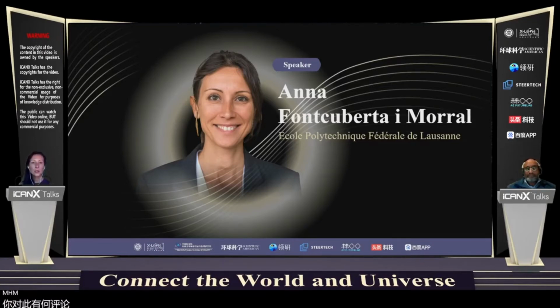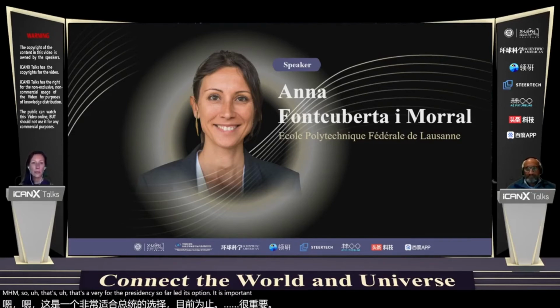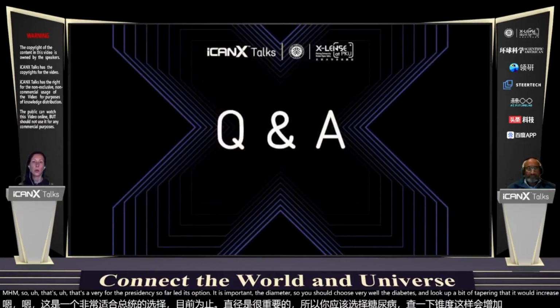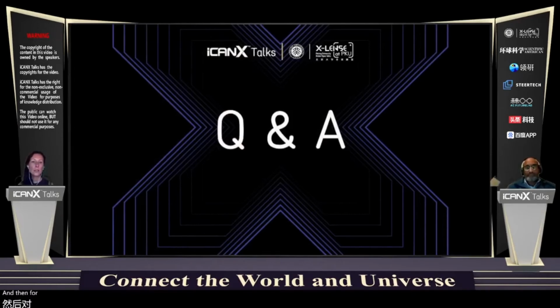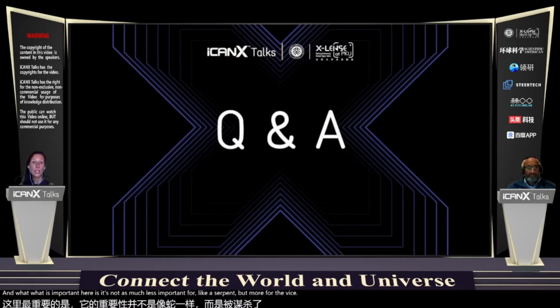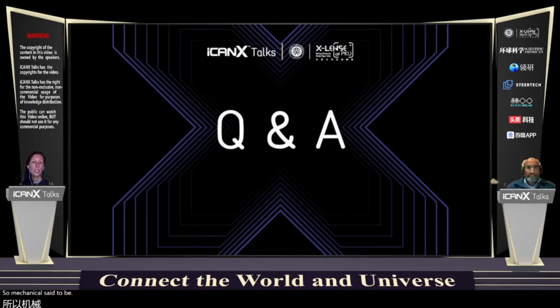So that's a very important question indeed. For light absorption, the diameter is important. You should choose the diameter very well, and if you have a bit of tapering, then you would increase the broadband absorption. The aspect ratio would be the ratio between the diameter and the length. For the length, it is much less important for light absorption, but more for device fabrication. If you have too long nanowires, you would have higher absorption and be able to space them more, but then during fabrication they will break. So mechanical stability is an issue. So 2 microns is quite good to make devices without breaking them.